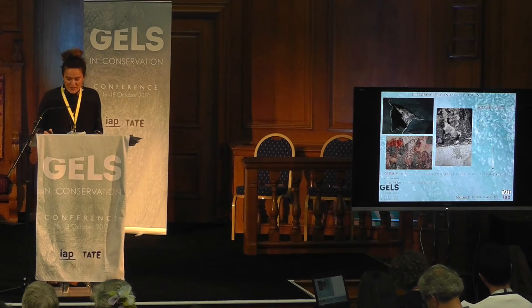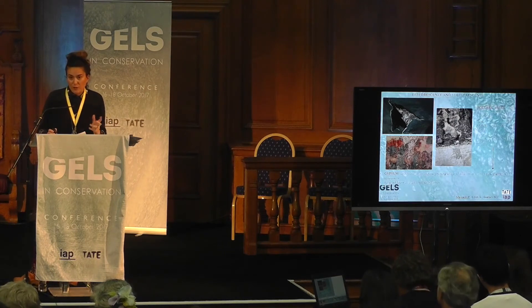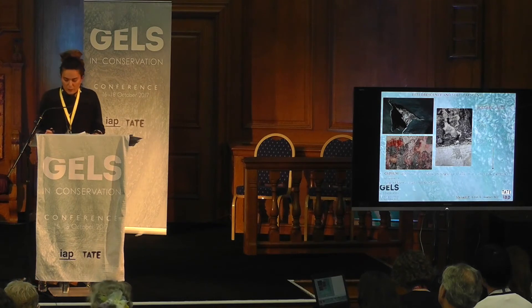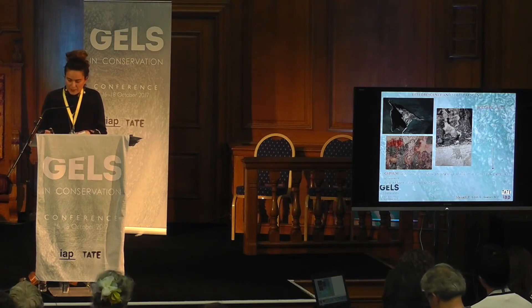There was also flaking everywhere. Furthermore, because the original structure was made of concrete and the original priming was basically gypsum, with original pigments and colorants based on gypsum as an additive, there was a large amount of soluble and insoluble salts — specifically potassium, sodium, magnesium, and calcium sulfate, as detected by X-ray diffraction.